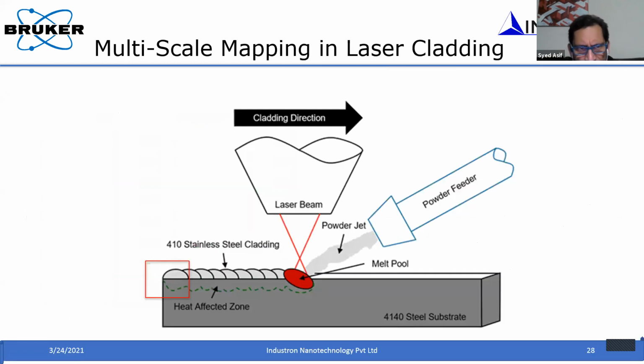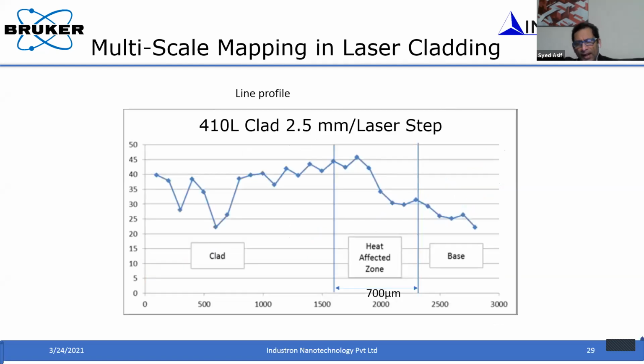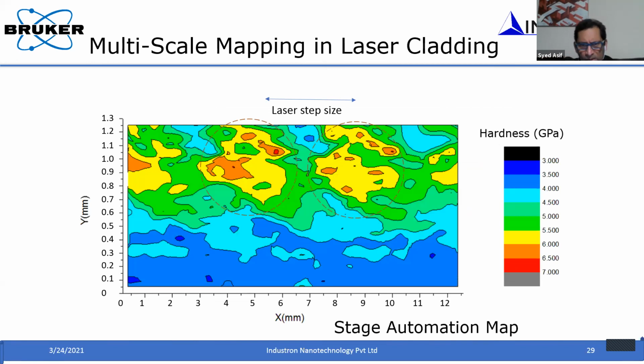Okay. Another example, this is a multi-scale mapping in laser cladding. When you do laser cladding, basically you have a powder jet, which is a steel powder, and then you melt it with a laser beam, and then you deposit it on the steel substrate. Now, if you wanted to understand how the property is changing at the interface, from the clad to the base, you take a typical Vickers hardness tester and measure the hardness as a function of distance, and then you get this kind of a line profile. This is how you get very coarse information on the property response. And if you do it in an array format with the micro hardness tester, you probably get an image where you can see the region where the hardness variation is repeatable.